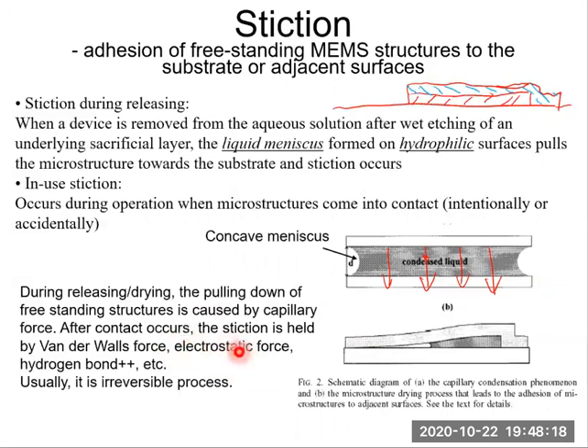Why? Because now the contact or the stiction is maintained by other forces, such as the van der Waals force, electrostatic force, hydrogen bond. Those forces are not dependent on liquid. The capillary force or meniscus force is caused by the trapped liquid. So after it's completely dry, this capillary force disappears. But now the cantilever is held, this stiction is maintained and held by other forces.